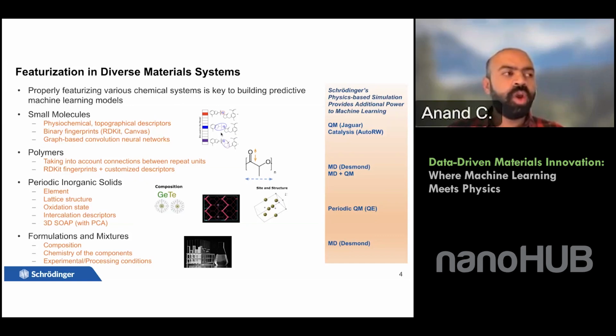And if you want to avoid DFT, I can think of a few strategies. One is using semi-empirical descriptors like MOPAC and XTB. These semi-empirical descriptors are quite fast, not as fast as 2D, but they're definitely much faster than DFT. For a molecule, it takes a few seconds or a minute or so to get these descriptors. And with semi-empirical descriptors, you can get HOMO-LUMO values, polarizability, molecular hardness, and things like that. So those descriptors could potentially be useful if you want to avoid the expensive nature of DFT.